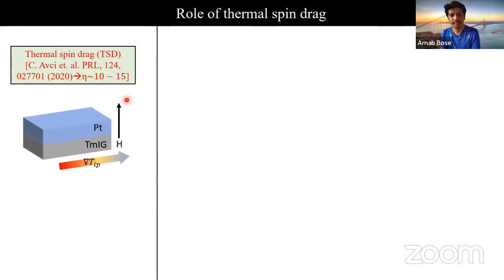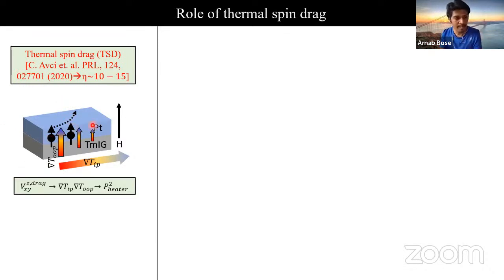So it was explained with the thermal spin drag mechanism. Let me explain what it is. When we try to create in-plane thermal gradient, we naturally get some out-of-plane thermal gradient, which will inject out-of-plane spins. And while these spins are driven along the in-plane thermal gradient, they can deflect sideways, and that leads to a second-order Hall voltage. That would be proportional to both the in-plane and out-of-plane thermal gradient, so it would be proportional to the square of the heater power.